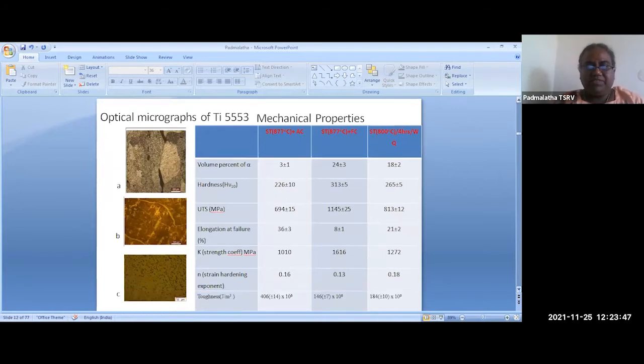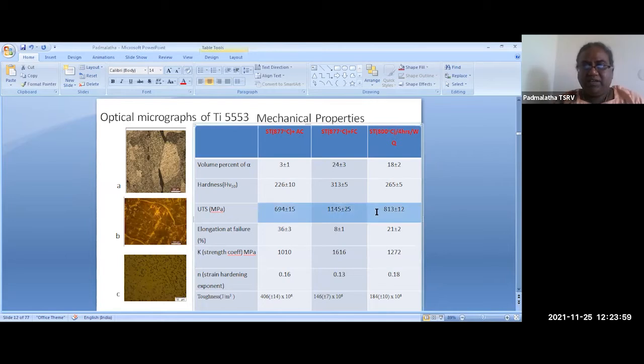And I have subjected it to 3 different heat treatment conditions, though the alloy is the same. By subjecting it to 3 different heat treatment conditions, we can clearly see how the properties are changing. As we all know, by the annealing process, that is furnace cooling, the material will usually become soft. But in this case, in our material, the strength of the material is increasing.